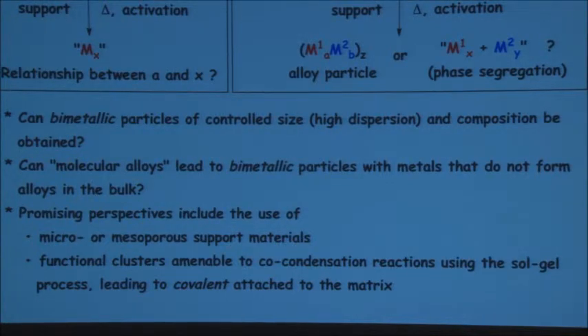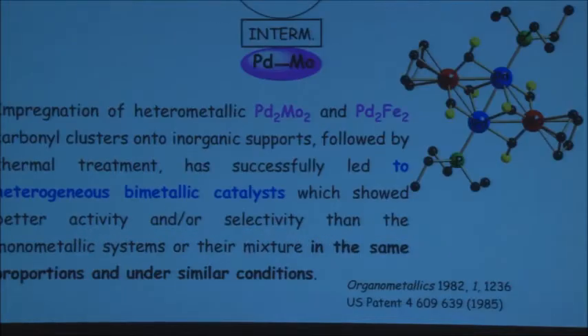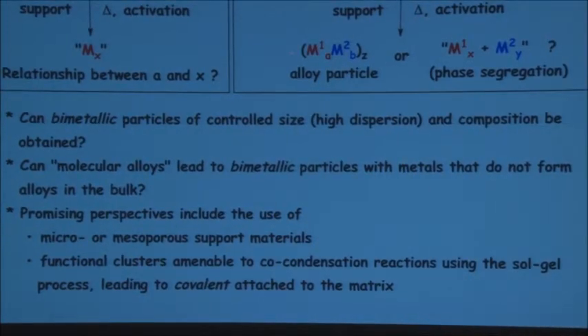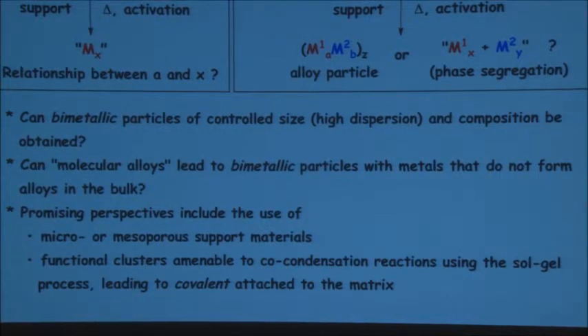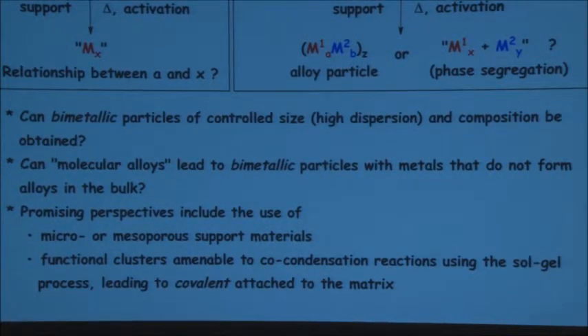You can even think of making metal particles of metals that are not miscible in the bulk. If you take, for example, ruthenium and gold, we can make mixed metal clusters with ruthenium and gold, but you cannot form an alloy. These two metals do not mix.